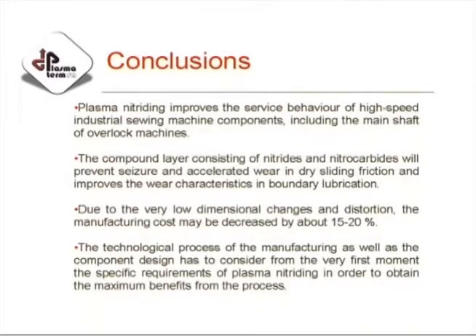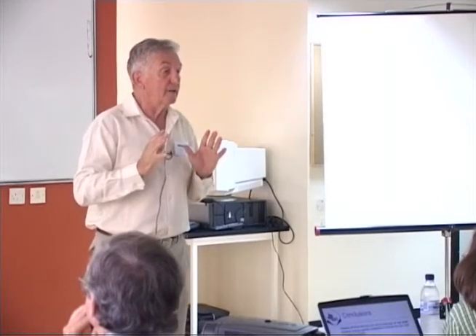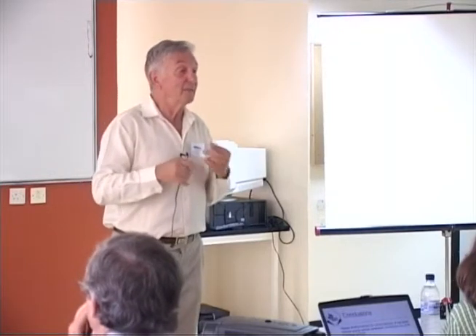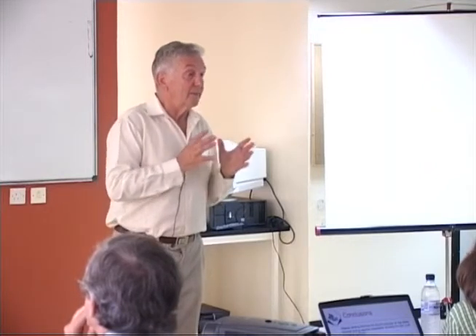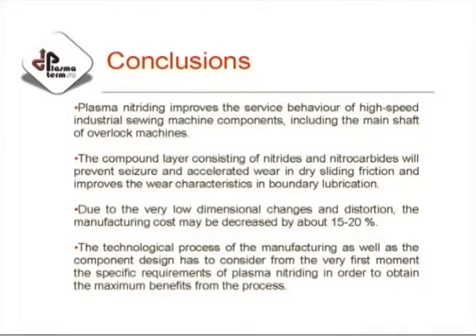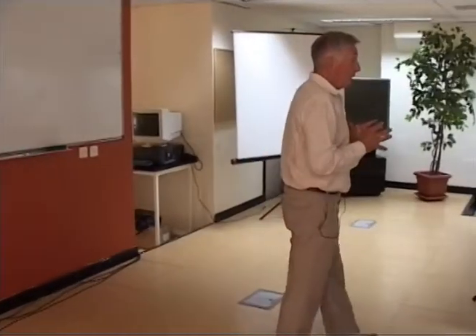The compound layer consisting of nitrides and nitrocarbides will prevent seizure and scuffing, so it will give a much better wear behavior than carburizing, even when lubrication will disappear for short times. This is a big problem in most of the textile makeup companies, so confectionery work, that the lubrication could be problematic sometimes, and especially when you start the machines, they practically run in dry conditions. And plasma nitrided components will give good results also in this case. And due to the low dimensional changes and low distortion, the overall manufacturing cost will be lower by about 15 to 20%. So that's what was, for us, a very typical case history, a very interesting one.